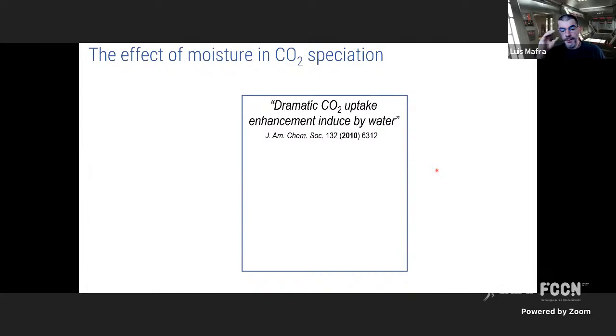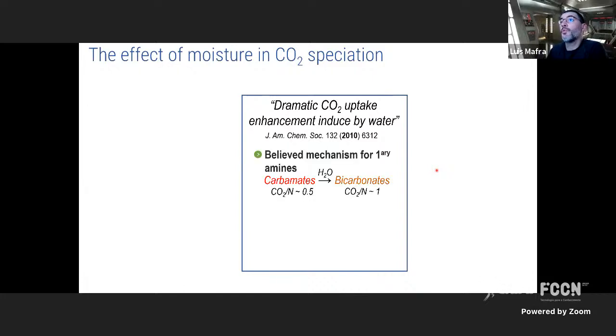The last problem I want to present is about the effect of moisture. Lots of work done in MOFs, COFs, and zeolites for CO2 capture concentrates on pure CO2, but pure CO2 doesn't exist in any source. CO2 is always mixed with something else, okay? And water is almost present in every gas mixture and is a big problem. There was a paper stating a dramatic CO2 uptake increase in wet samples, so we tried to understand why.